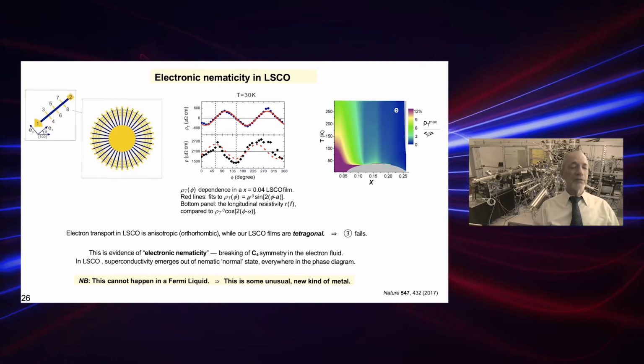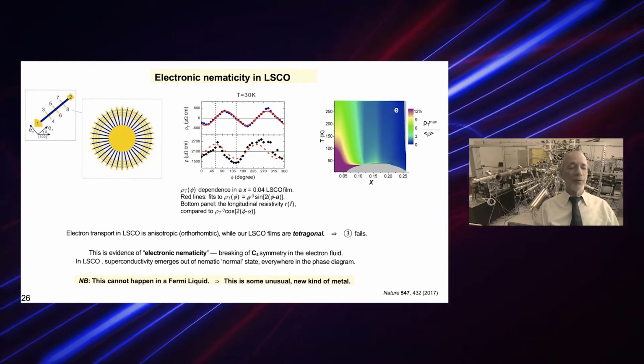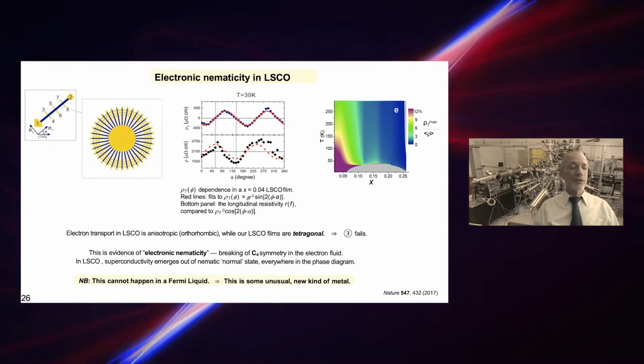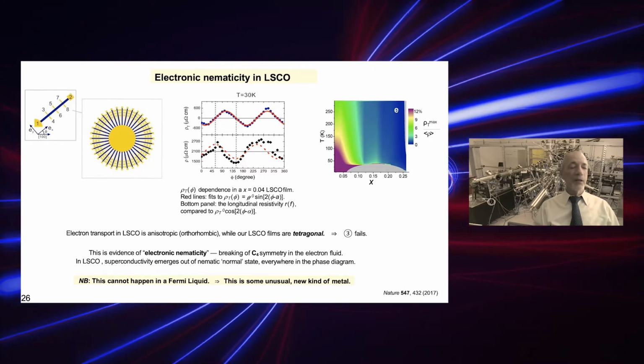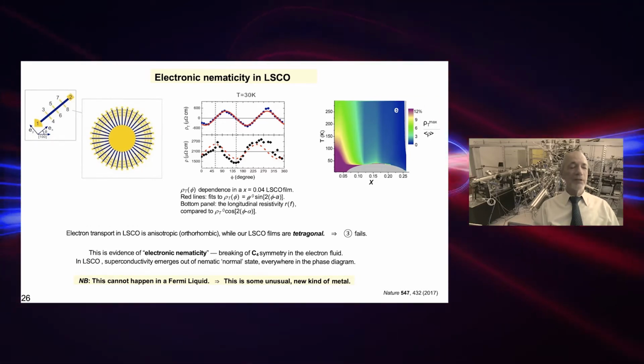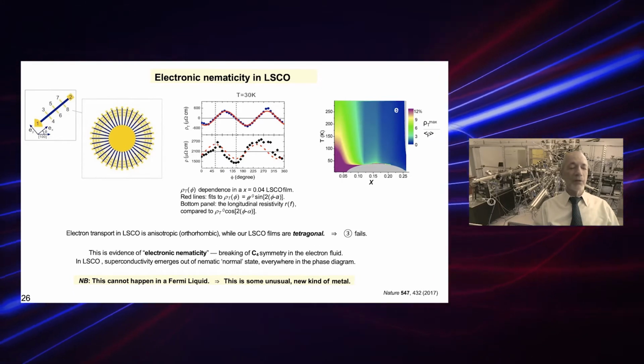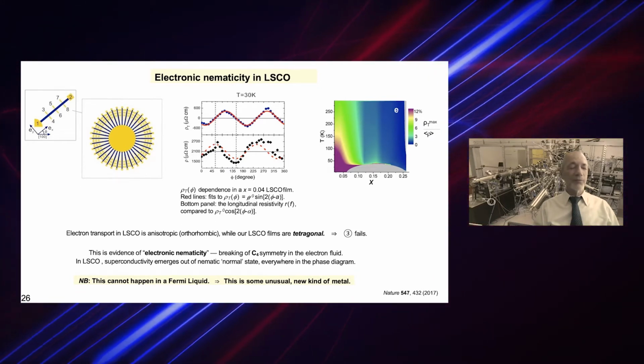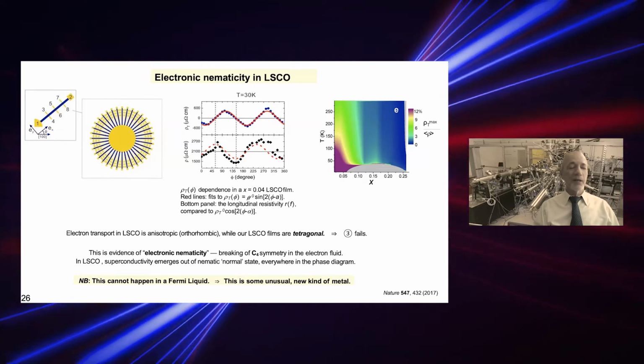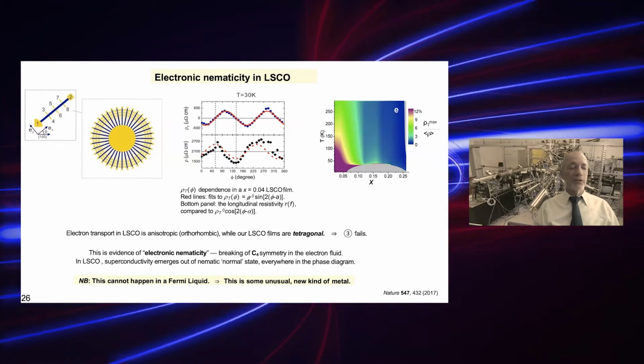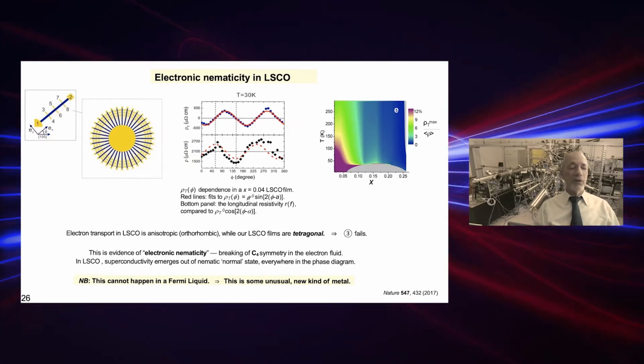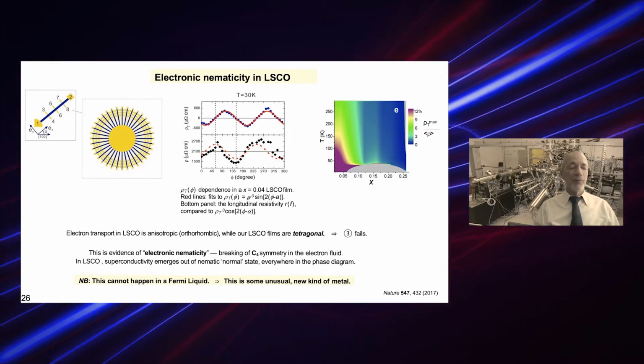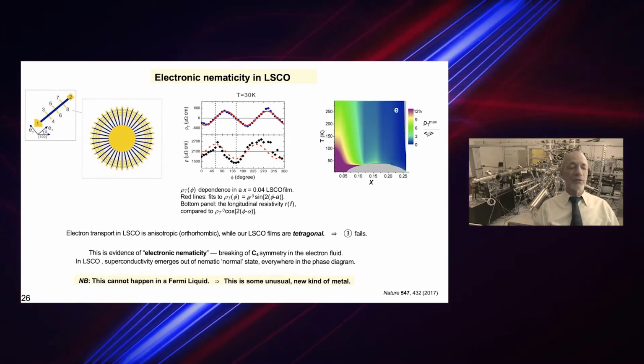This shows that the fourfold rotation symmetry is broken up to the room temperature and every doping, implying that the resistivity tensor is always orthorhombic. Note, however, that our films are strictly tetragonal. They are epitaxially pinned to a tetragonal substrate, and we have verified this by high-resolution synchrotron X-ray diffraction.